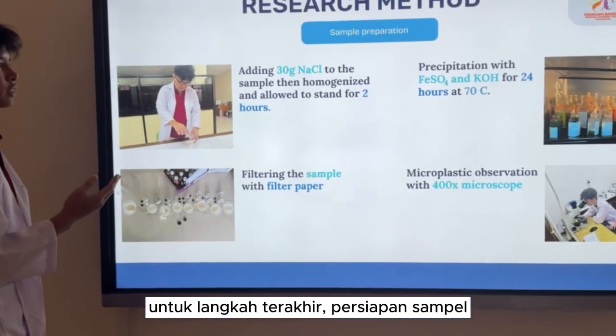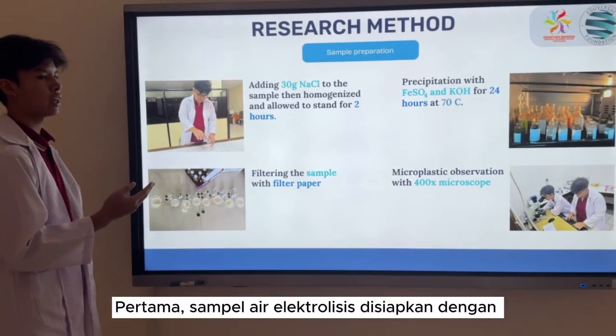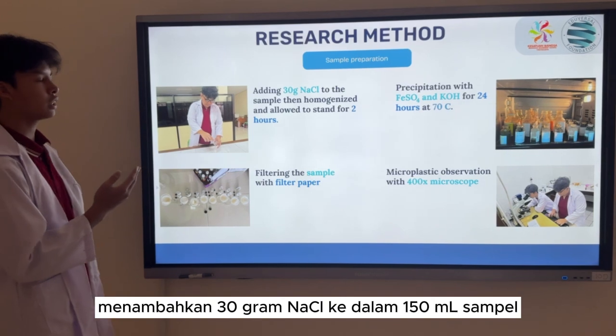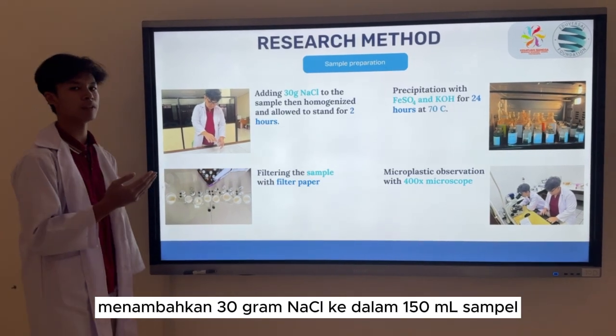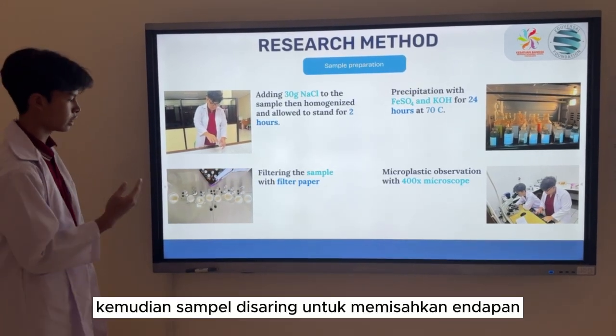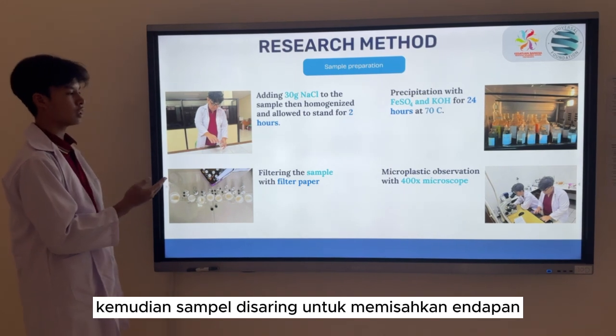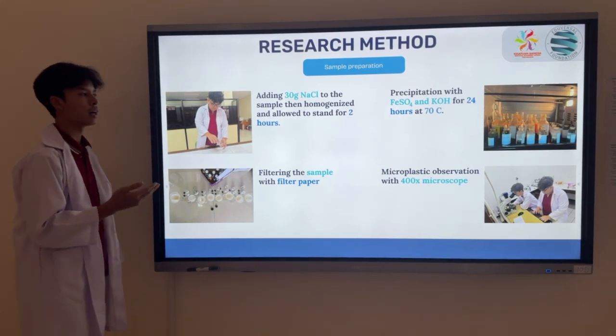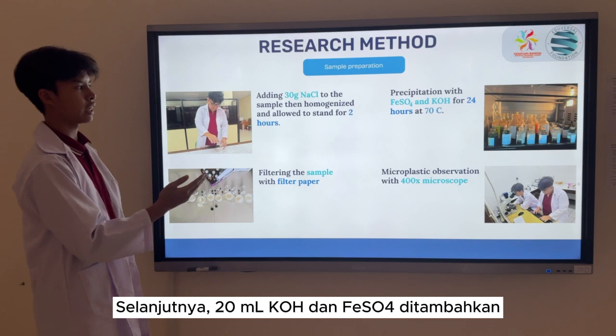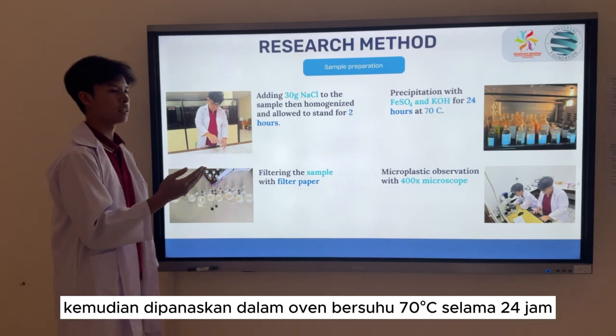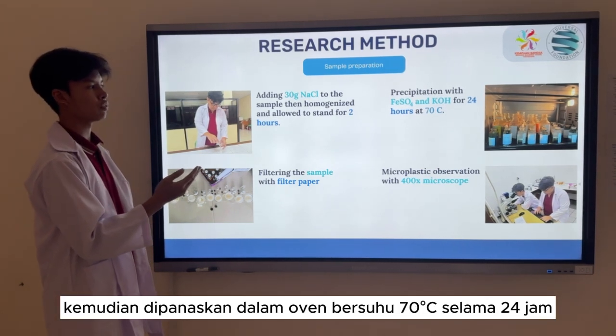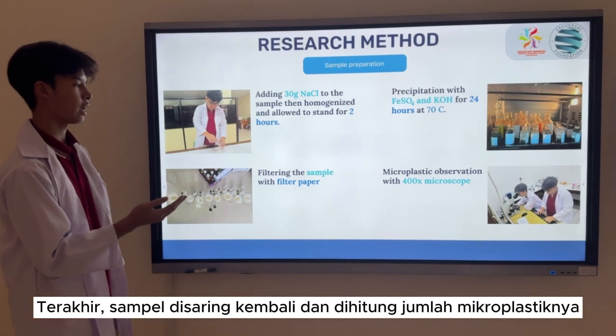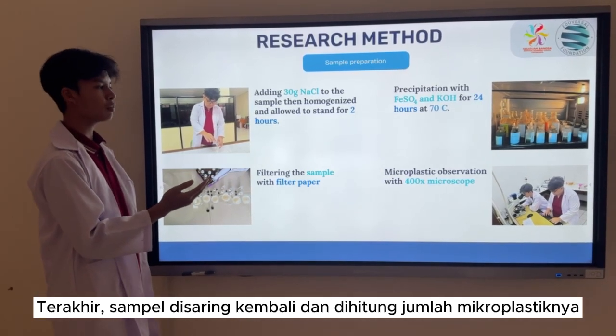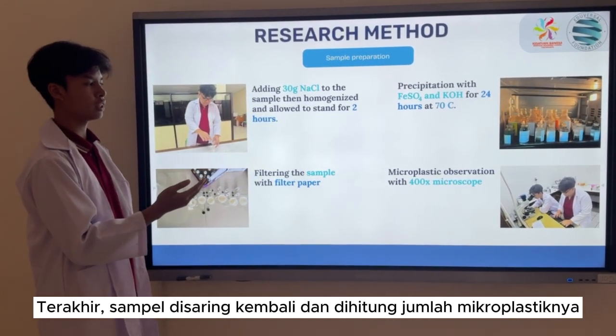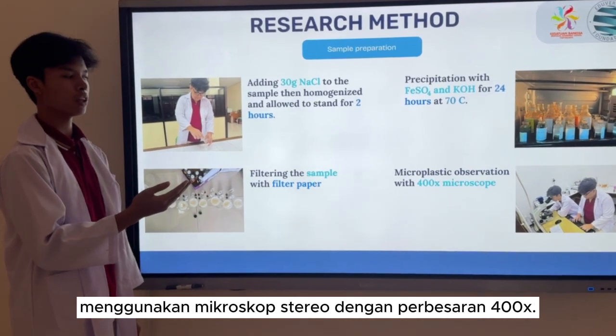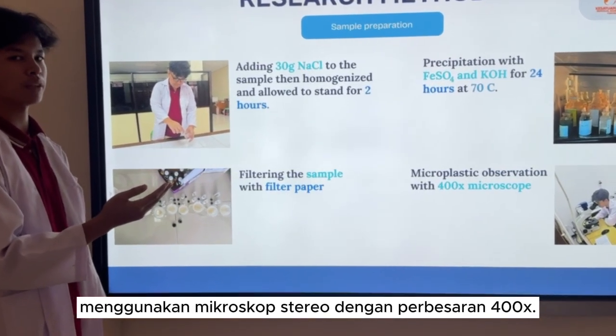Next, the sample preparation. First, electrolyzed water samples were prepared by adding 30 grams of NaCl to the 150 ml of the sample. And then, the sample will be filtered to separate the sediment. Next, 20 ml of KOH and Na2SO4 were added. Then, heated in a 70 degrees Celsius oven for 24 hours. And lastly, the sample was filtered again and the microplastic were counted using a stereo microscope with 400 times magnification.